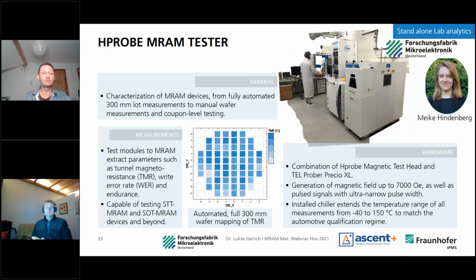The other metrology tool we have here that is dedicated to MRAM is the H probe. It's characterization for MRAM devices. Also 300 mm wafer capable, and you can of course do automatic or manual wafer on coupon level. You will test tunnel magnetoresistance, the TMR, write error rates, and endurance, and it's possible for different MRAM approaches. So we have here a magnetic field. You can generate a magnetic field up to 7,000 Oersted, as well as have pulse signal and use a stage that can be heated or cooled.